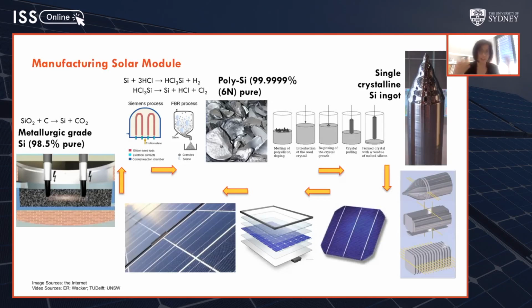Then the wafers receive surface coating to passivate the defects and for anti-reflection, and the metal is deposited. You see these white lines, they're actually metal deposited on the surface to conduct the electrons out for power generation. Then they are sandwiched between glass and a backsheet and form a rigid panel. Now they're dirt cheap to make, but they still require people to install the panels and the wiring and hook them up to inverters. So there's always incentive to increase the performance further, given the practical limit is only 30%.